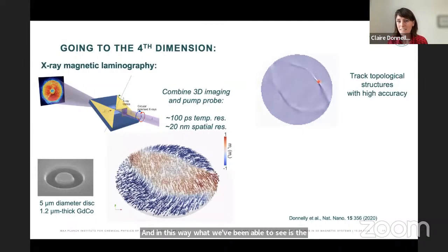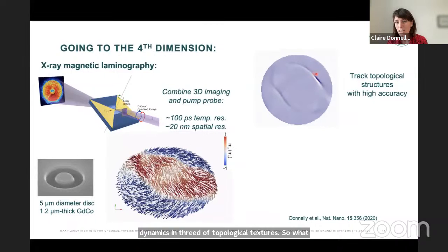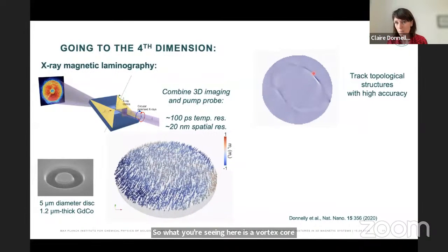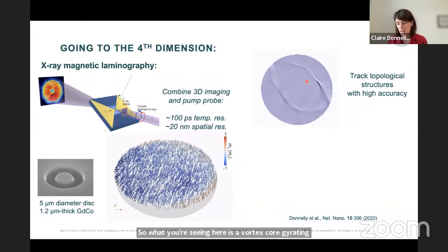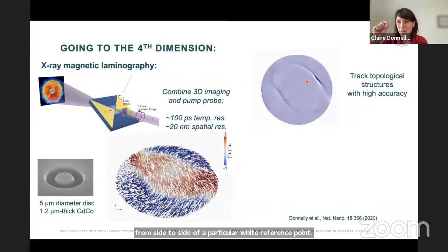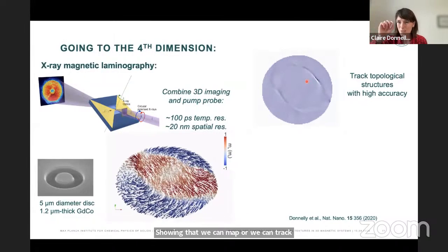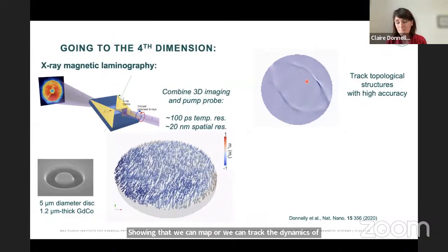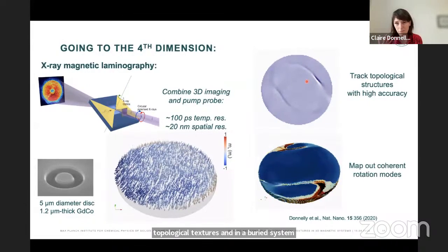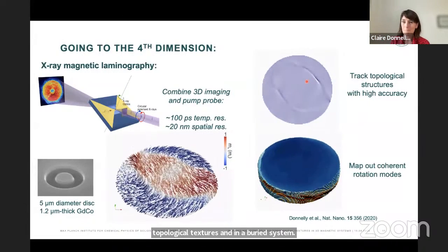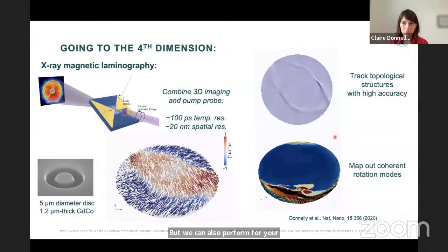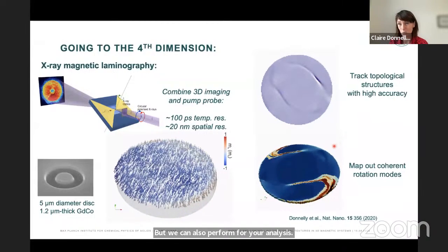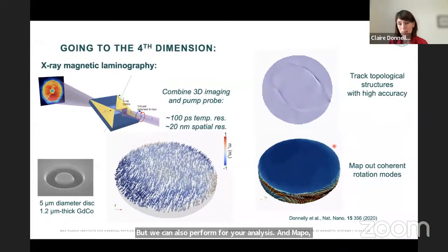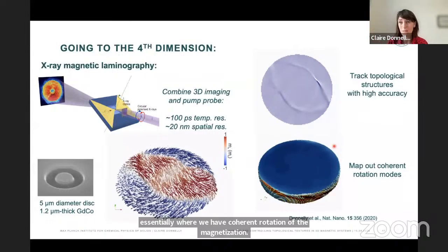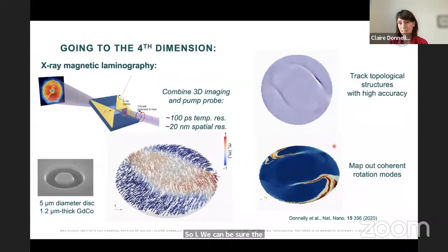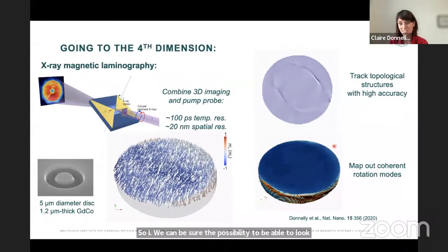So what you're seeing here is a vortex core gyrating from side to side of a particular white reference point, showing that we can map or we can track the dynamics of topological textures in a buried system. But we can also perform Fourier analysis and map out essentially where we have coherent rotation of the magnetization. So, i.e., we show the possibility to be able to look at the spin waves in magnetic configurations.